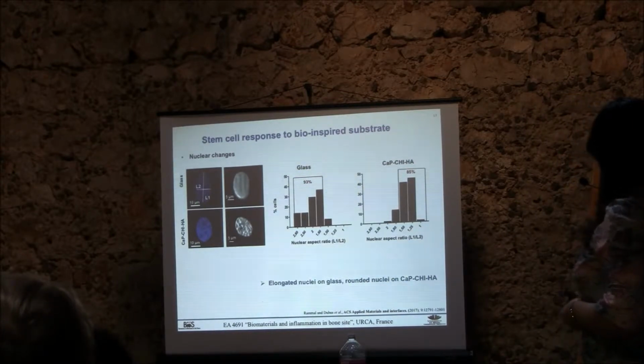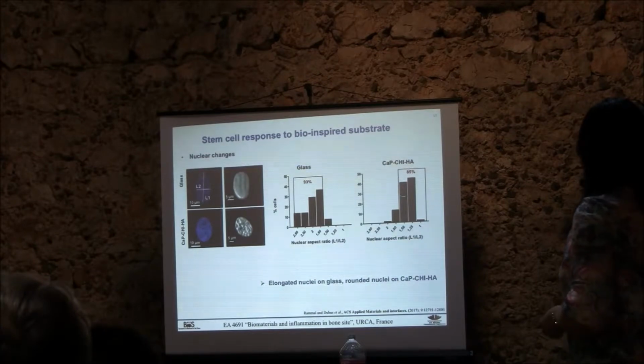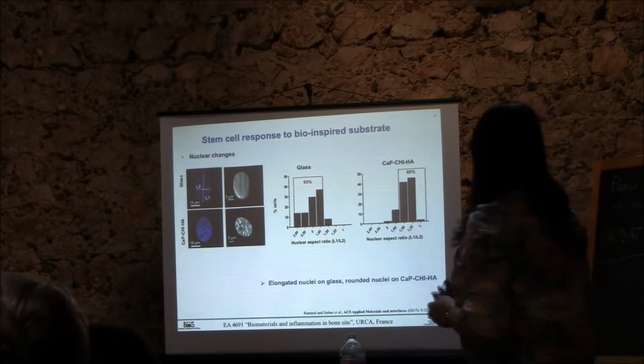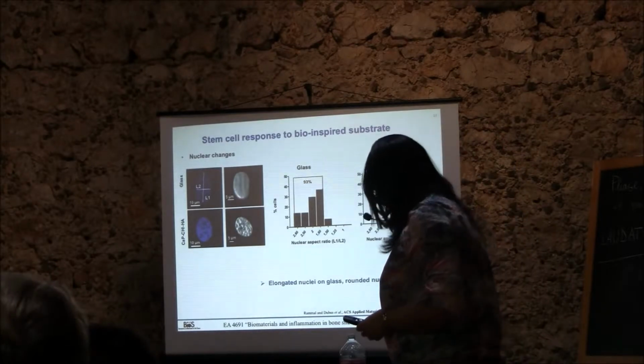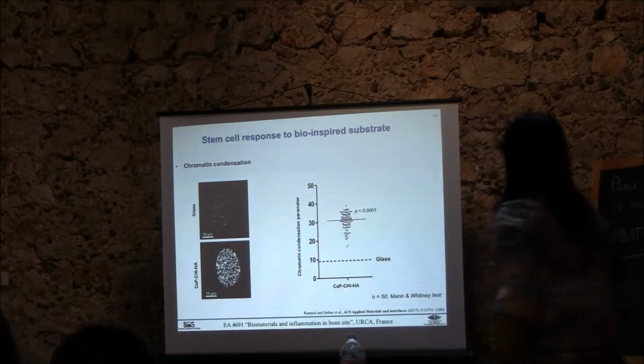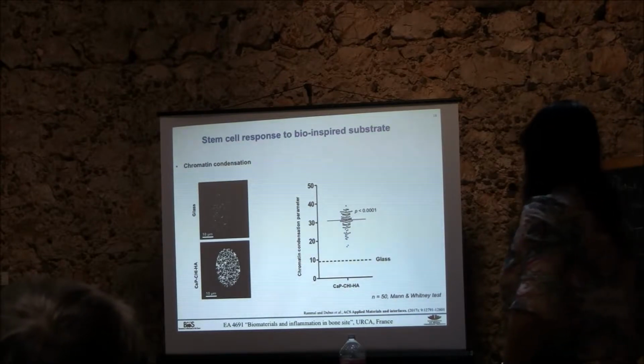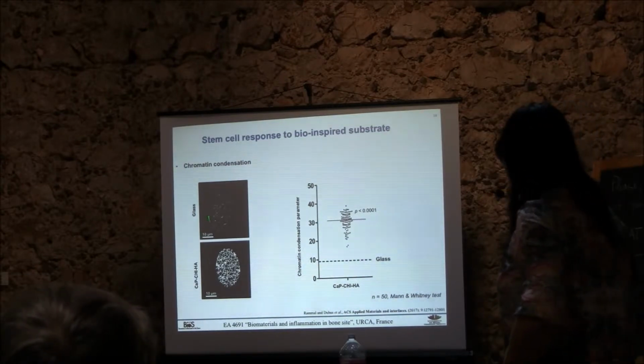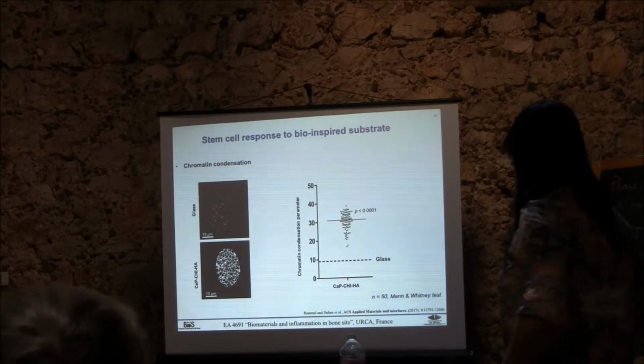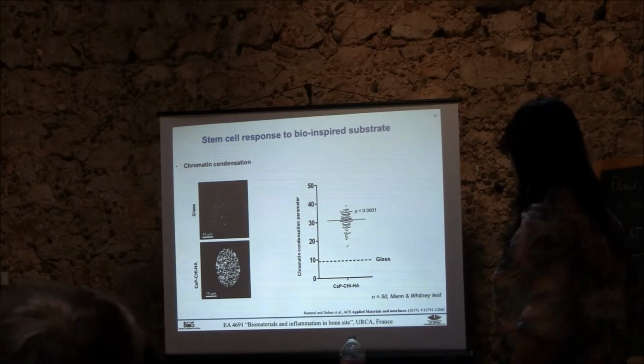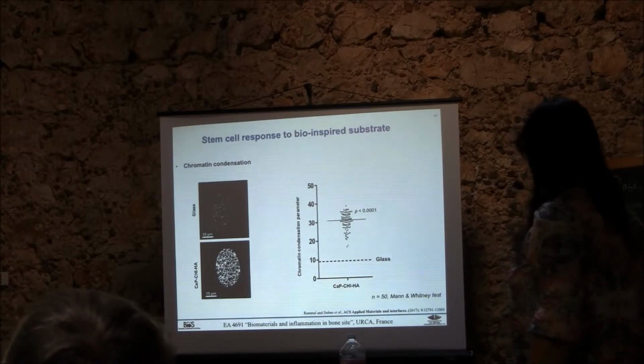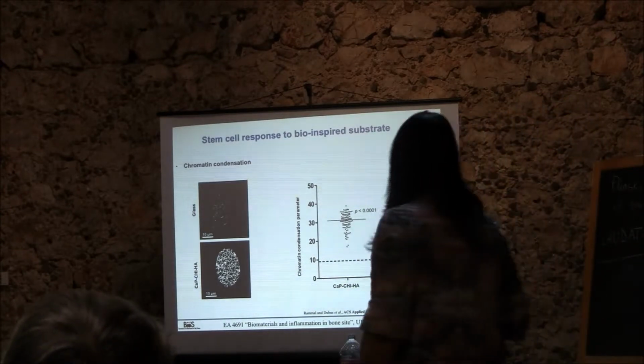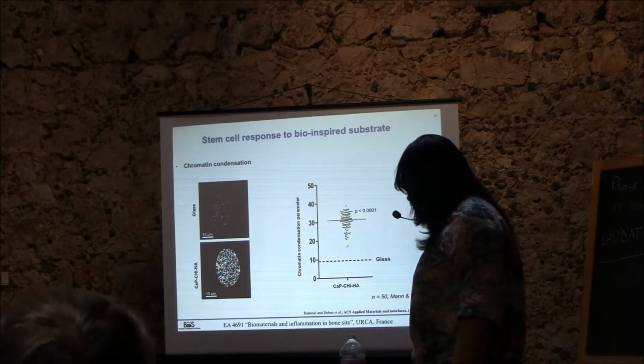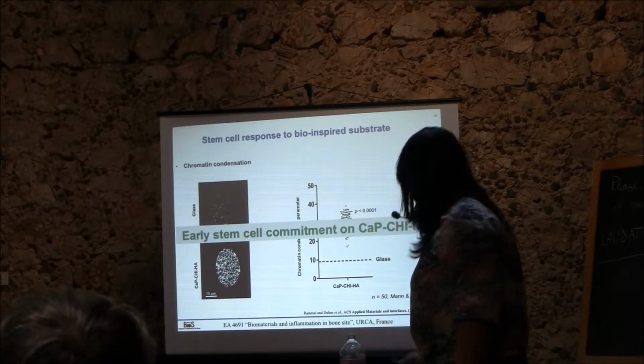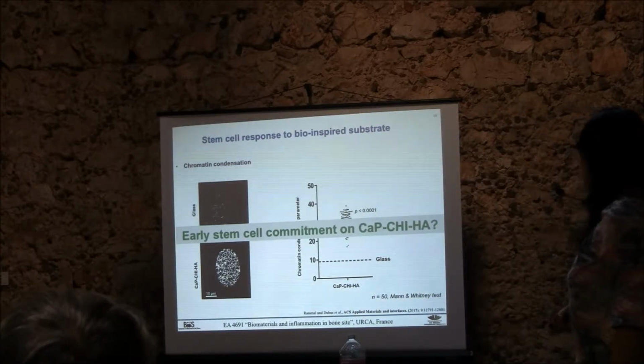In the glass, nuclei are elongated with a ratio of more than 1.80. So we measured chromatin condensation and observed a significant increase of chromatin condensation on our bio-inspired substrate. So chromatin condensation could mean an early stem cell differentiation on our bio-inspired surface.